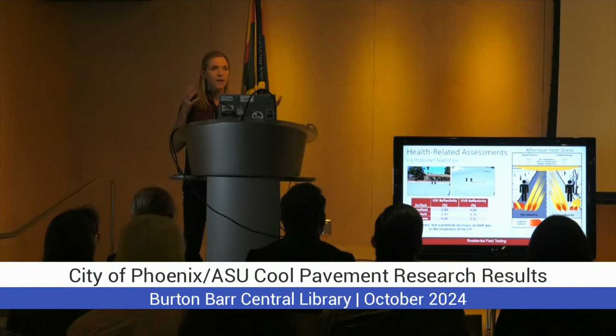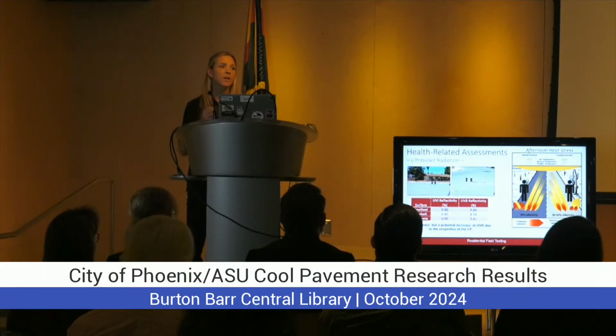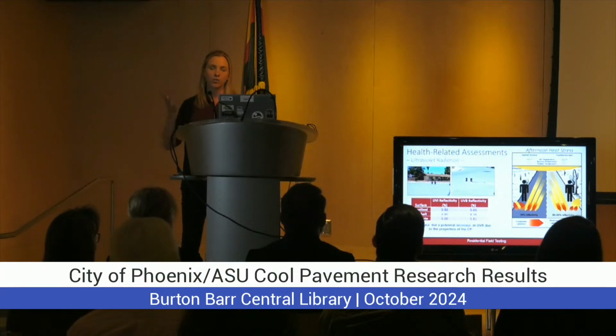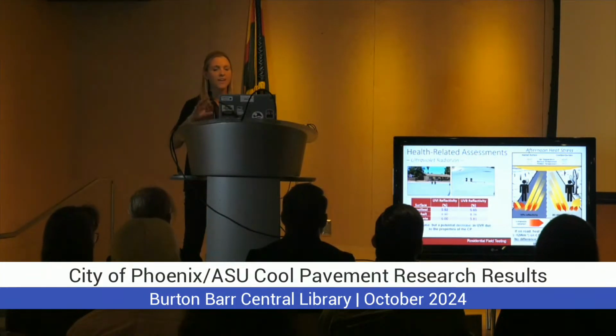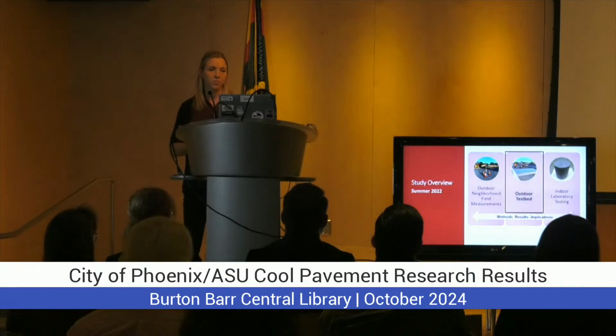And we created this little infographic for the report to be able to say, here's what's happening in terms of how the radiation for the different wavelengths is being partitioned on the surface. And so with that higher shortwave radiation over the surface, and thus the higher mean radiant temperature in the middle of the day, we did some heat stress measurements to see a slightly but insignificant higher heat load on a person if they're walking in the middle of the street. There's no difference in the morning, evening, or if you're walking on the sidewalk.